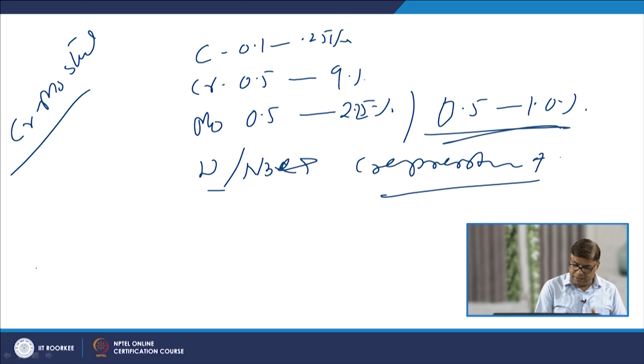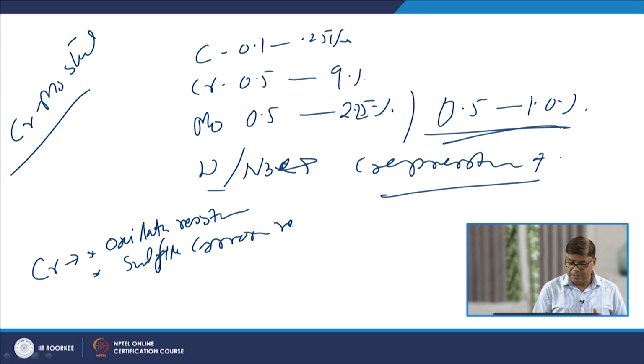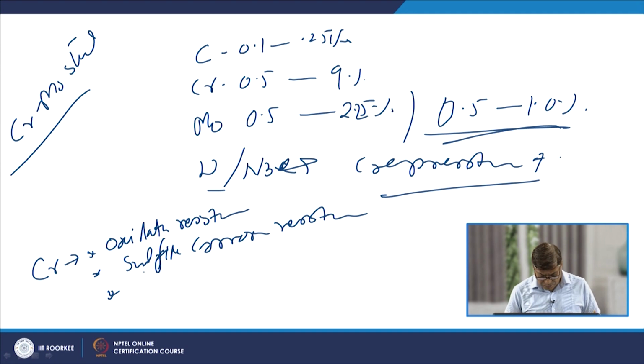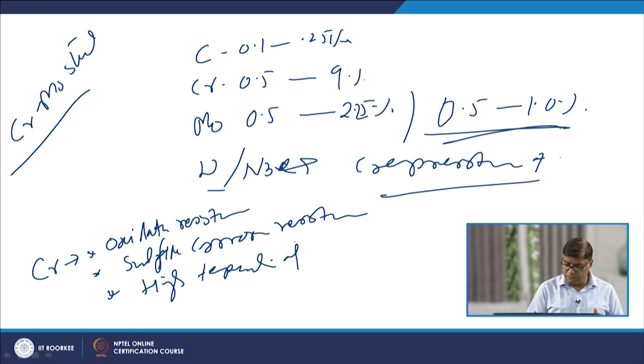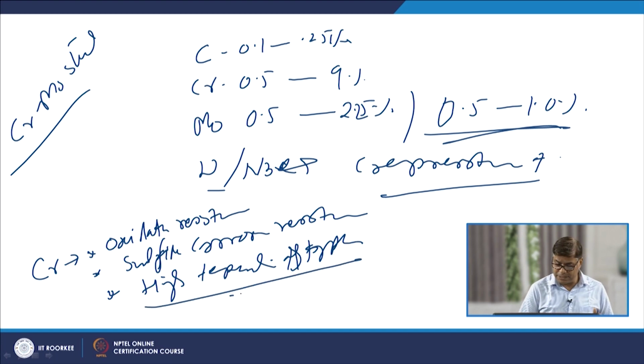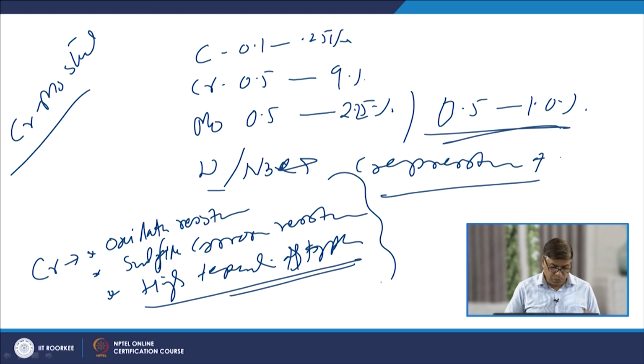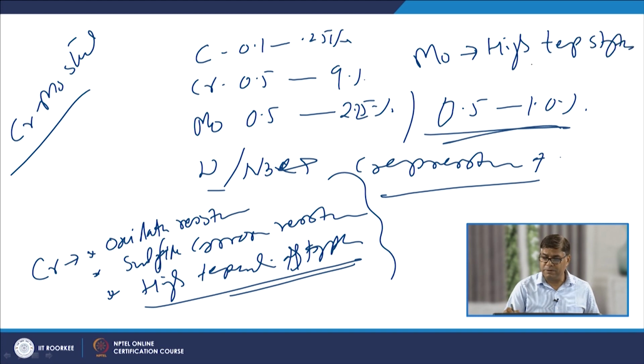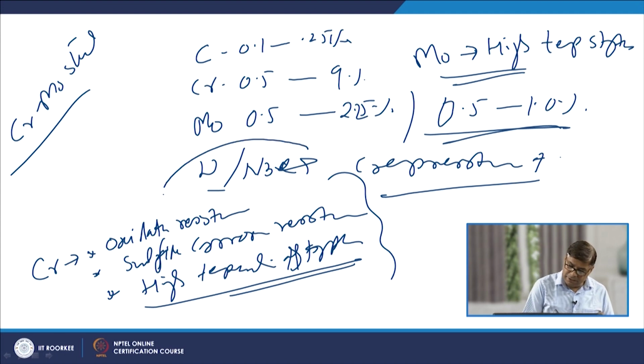Here each element plays a very specific role. Chromium offers resistance to oxidation, and sulfide corrosion resistance is also offered by the chromium, and it also helps in increasing the high temperature strength of the steel. So, these are the three important roles which are performed. On the other hand, when molybdenum is used, it primarily helps in increasing the high temperature strength of steel. And a similar kind of role is also performed by tungsten and niobium.